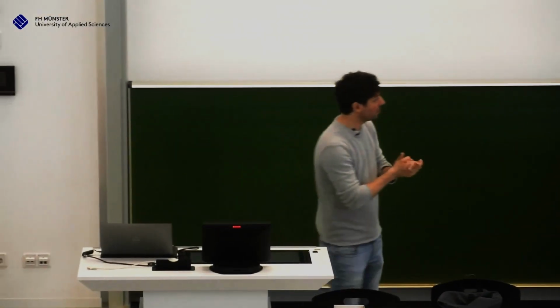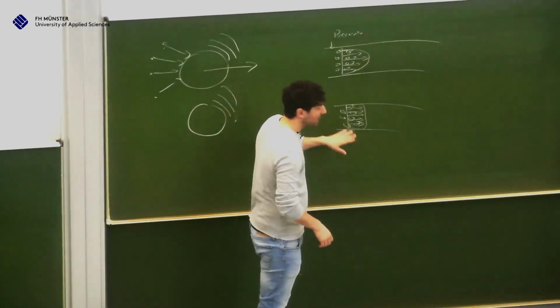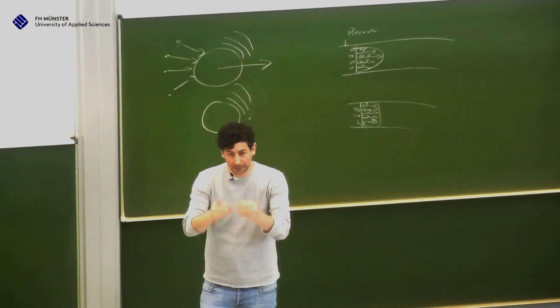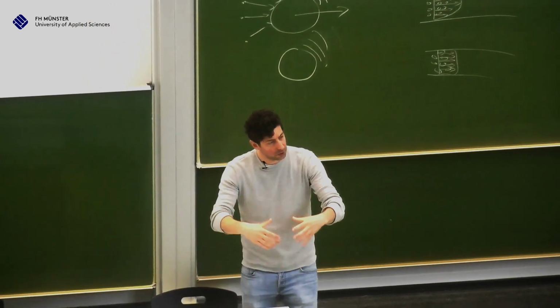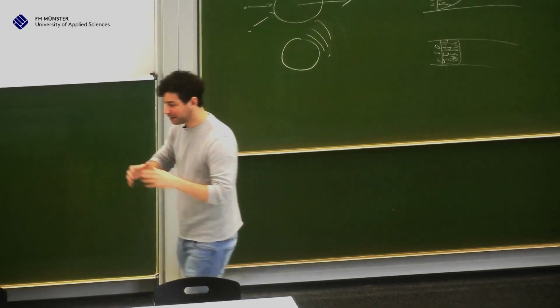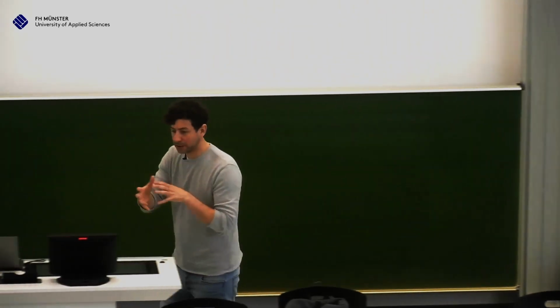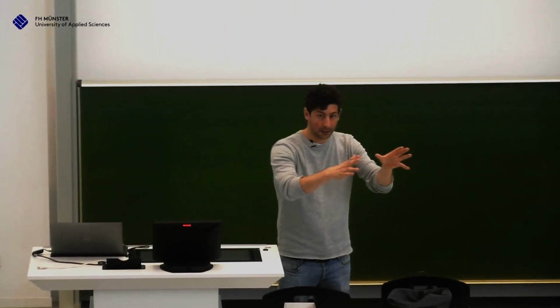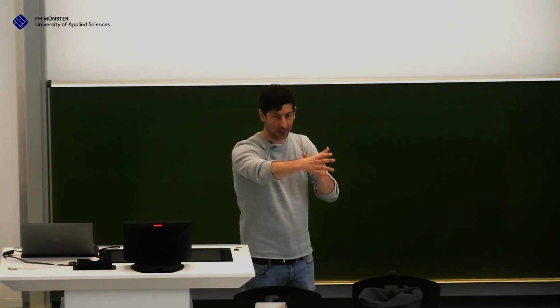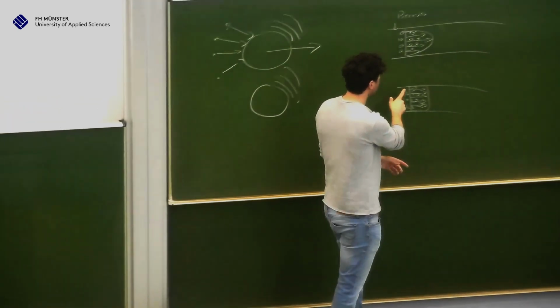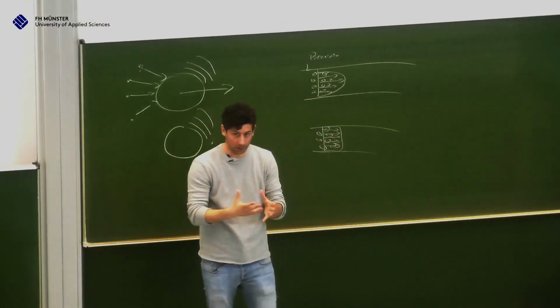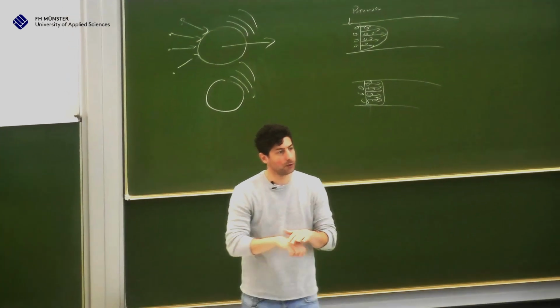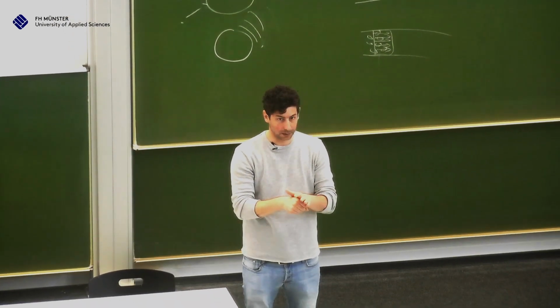And there's another thing: when you have larger particles, larger than 100 nanometer, the particles have a slip. And this means they are not exactly the same speed as the gas. They are a little bit slower because they are big. And this means if not everything from the precursor perfectly reacts away, it is carried away because it's faster. Okay, so you have a certain time for the reaction, everything is perfectly mixed, but for sure you will not have 100% reaction of your precursor. You will have leftover, and you like to put a little bit more because you don't want to have empty space on your particle, right?